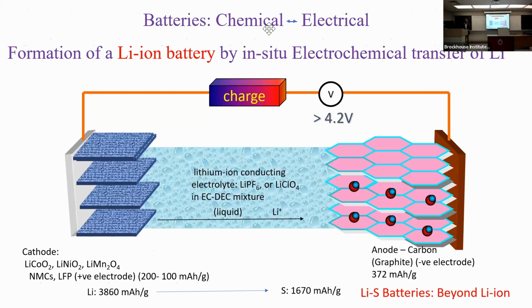So this structure that is shown on the right-hand side is able to intercalate lithium into the structure. On the left-hand side it's an oxide, could be lithium cobalt oxide, being the most common one at the moment for all the batteries that we use in our laptop and mobile phone, and the other chemistries that are following, especially for electrical vehicle applications. And these are also layered structures. As a result, they intercalate lithium into the structure and deintercalate.